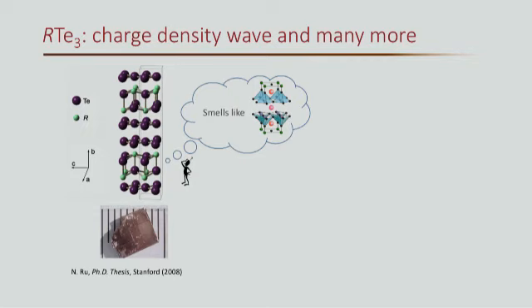Here, I want to emphasize that even though it's almost a square, it's not exactly a square. So A and C, the two in-plane axes, differ by a tiny little bit. That's why when you cool down the sample, the charge density wave always has a preferred direction to form. That's why it's stripe order. It's not a spontaneous breaking of the A and C symmetry, but rather the lattice itself determines A and C are not the same to start with.